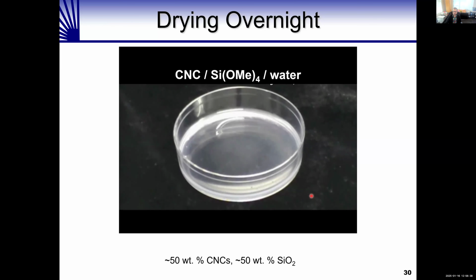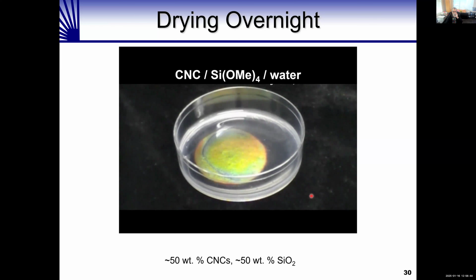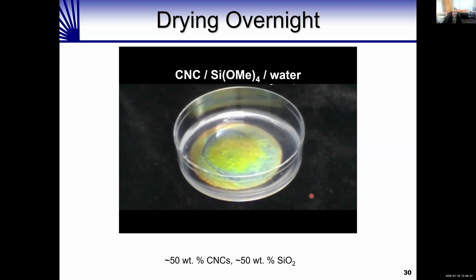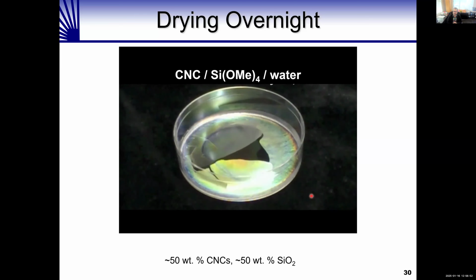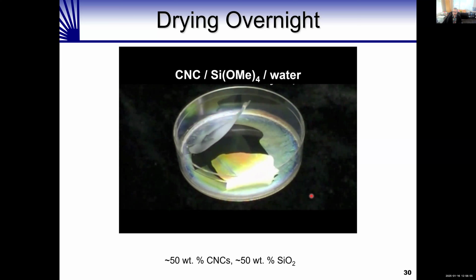Watch closely. Initially it's completely colorless, but you can see the color magically appear as those cellulose nanocrystals organize into this chiral-nematic structure. At the same time that the cellulose nanocrystals are organizing, that molecule tetramethoxysilane is condensing to give glass. We now have a film that's about half glass and half cellulose, and you can see the iridescent color, which tells us that the cellulose is organized into that chiral-nematic structure.